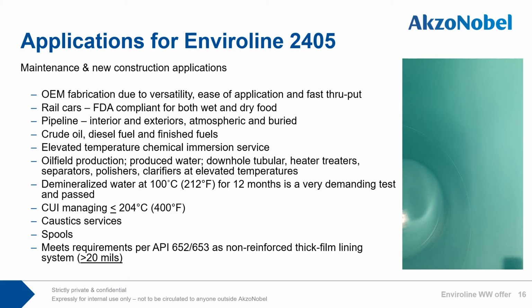Excellent at elevated temperature chemical immersion service. Also great in the oil field production. Produce water, downhole tubular, heater treaters, separators, polishers, clarifiers, and at elevated temperatures. Demineralized water. Very tough test at 100C for 12 months and passed. Manages under insulation at 204 degrees C. Resistant to caustics. Spools. Meets requirements of API 652-653 as a non-reinforced thick film lining system.